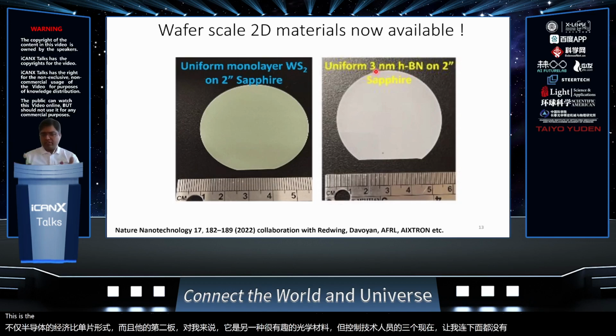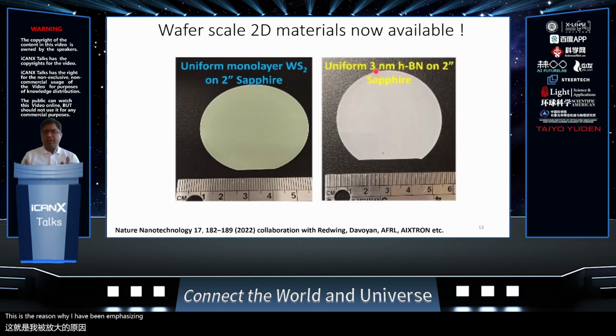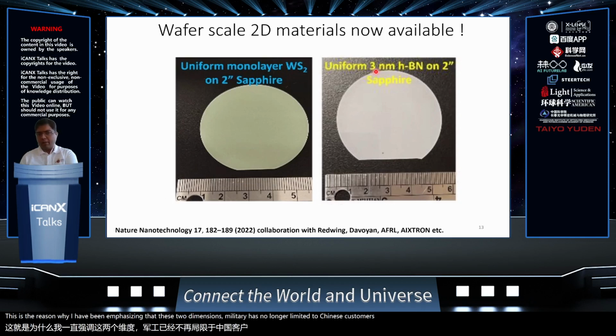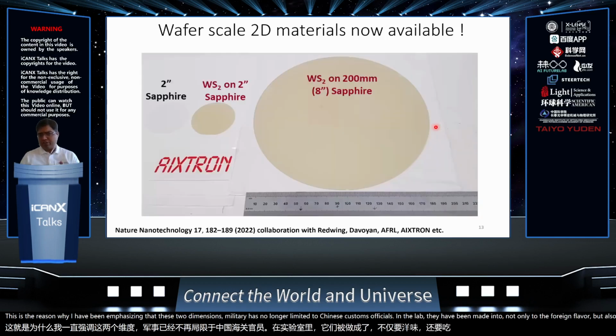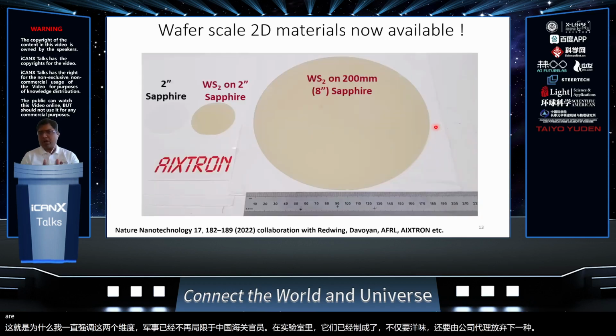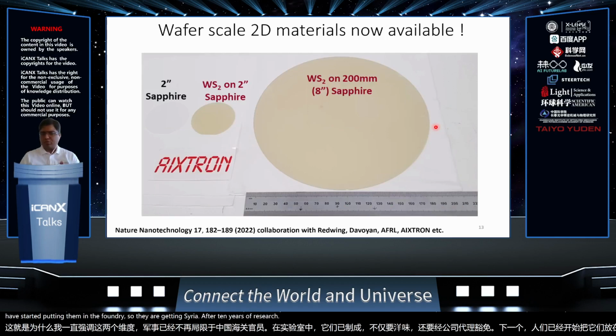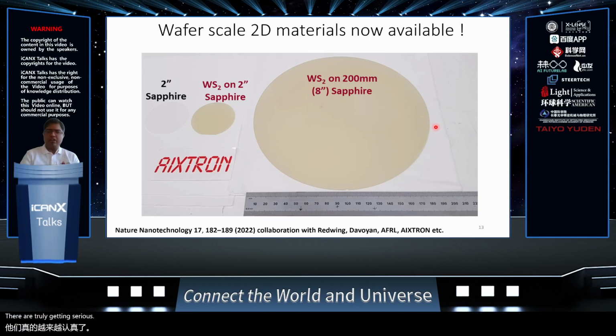This is the reason why I have been emphasizing that these two-dimensional materials are no longer limited to tiny Scotch tape crystals in the lab. They have been made into not only 2 to 4 inch wafers, but also 8-inch wafers by companies such as AIXTRON. People have started putting them into foundries, so they are getting serious. After 10, 12 years of research, they are truly getting serious in terms of scalability.